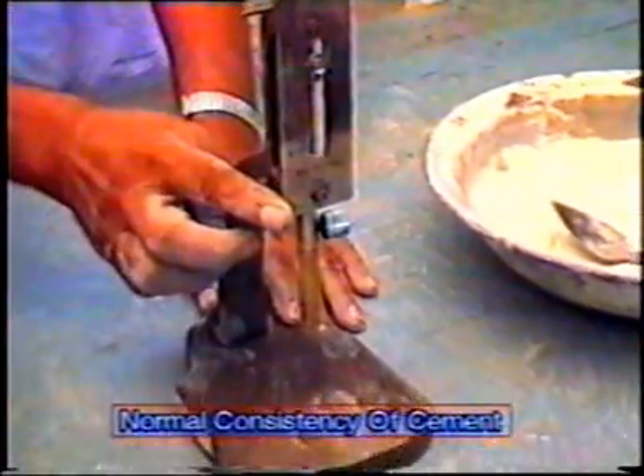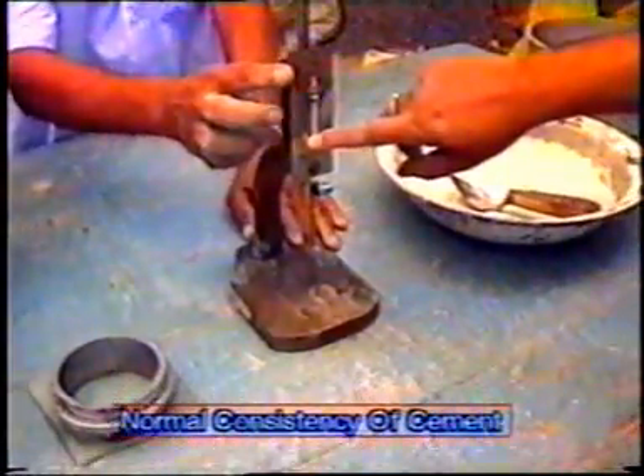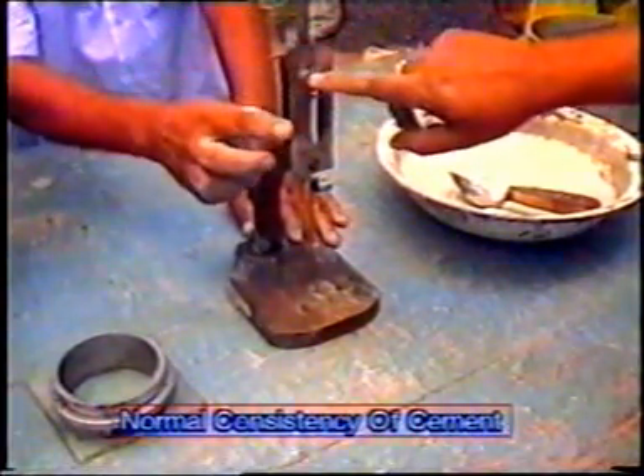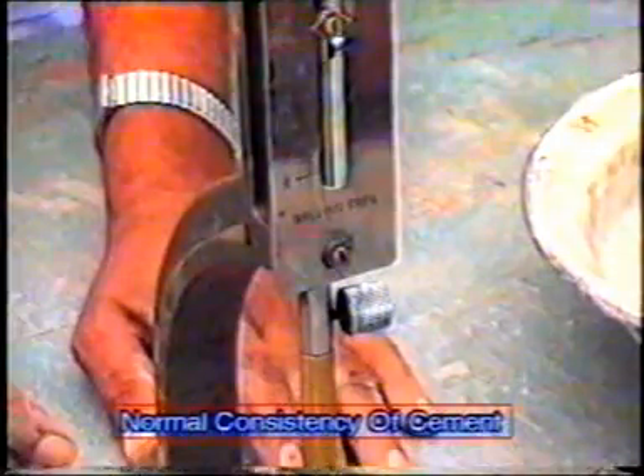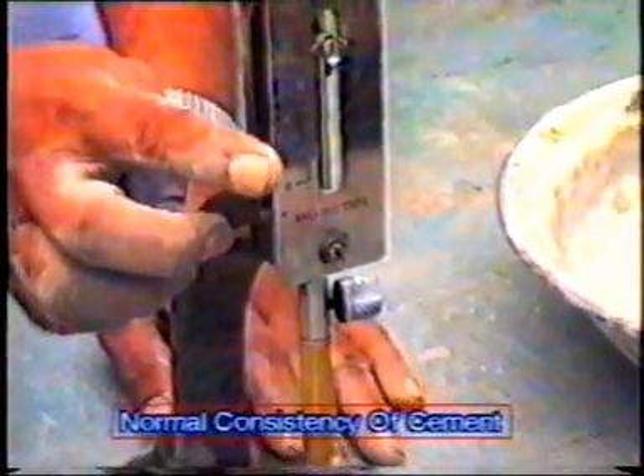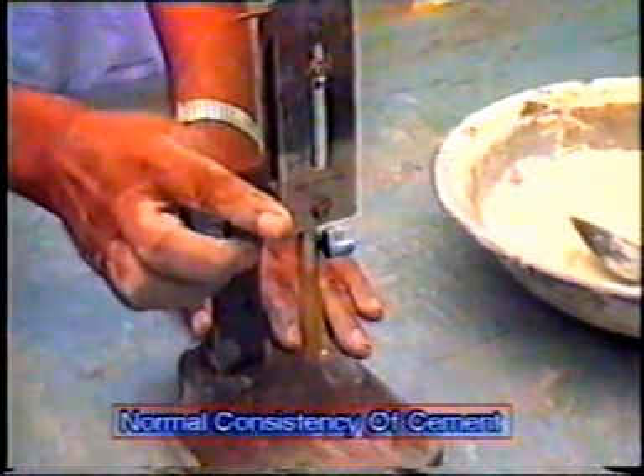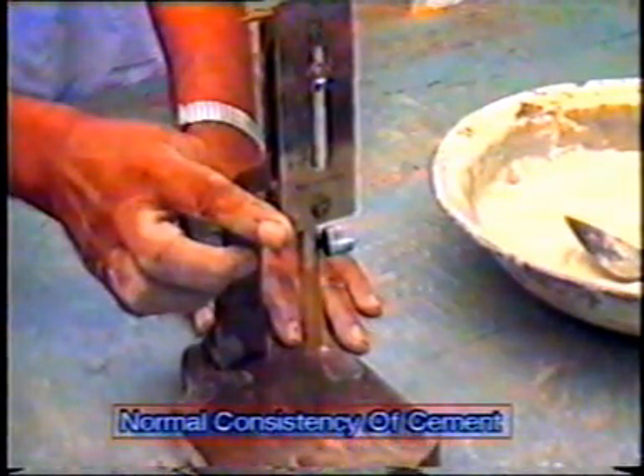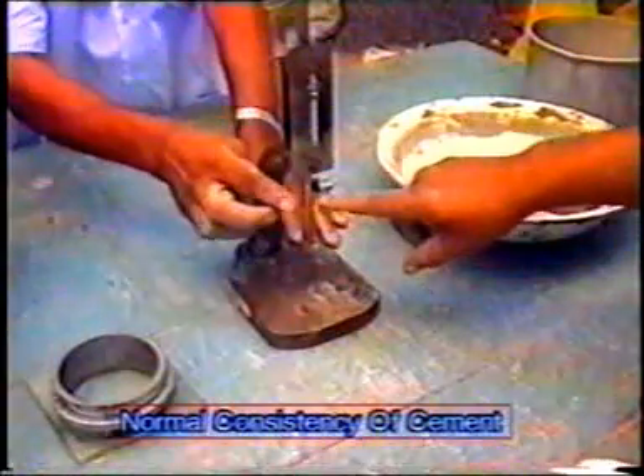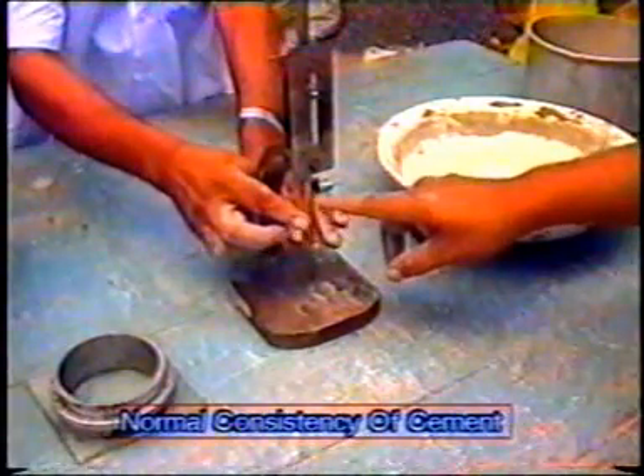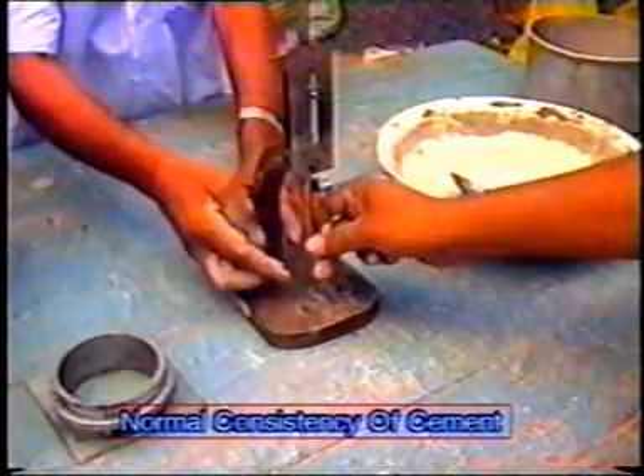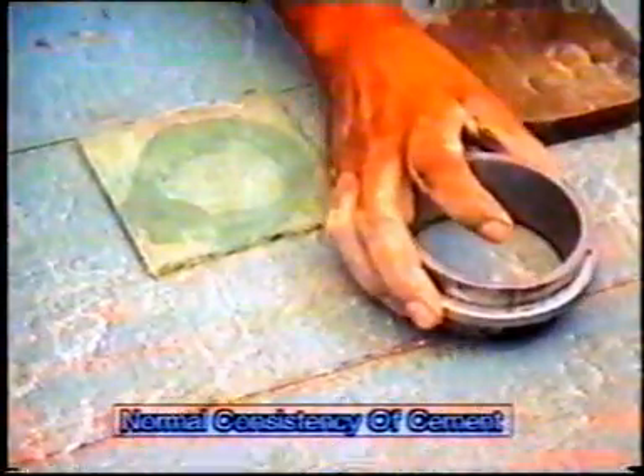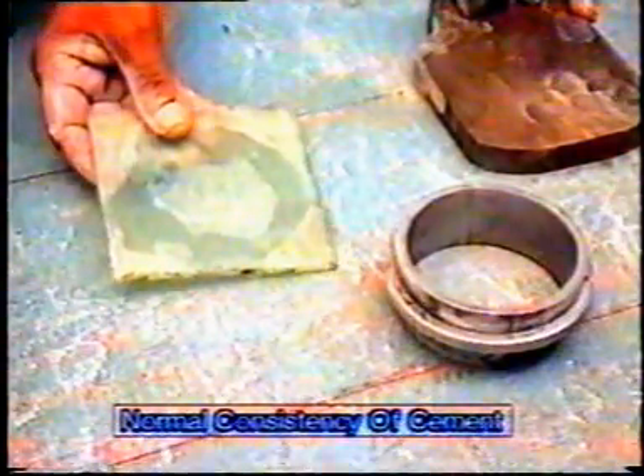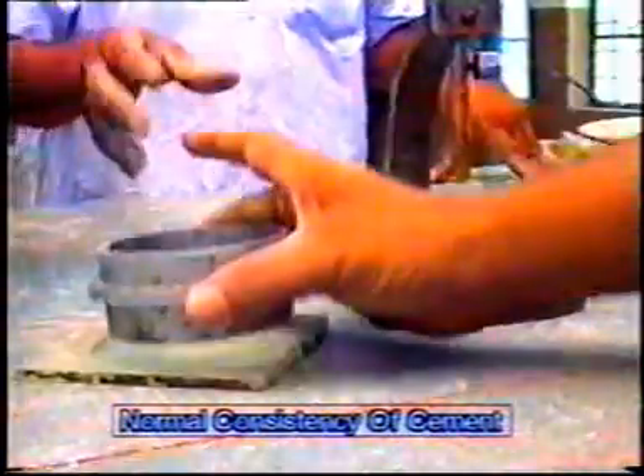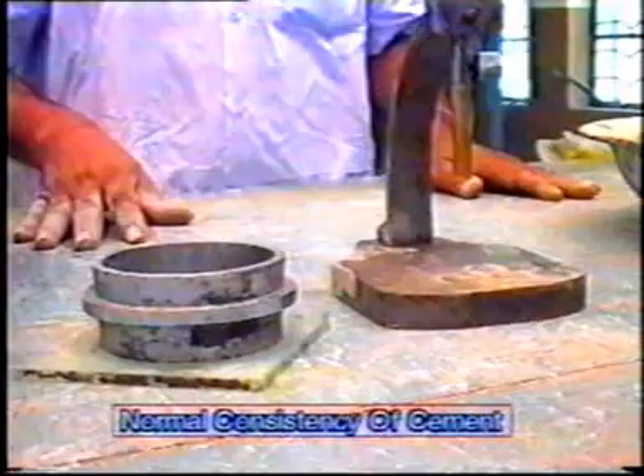Number 1, Vicat's apparatus, which is as per IS 5513/1968, whose penetration values are graduated from bottom to top, that is 0 to 50. Number 2, plunger of 10 mm diameter and 50 mm long. Number 3, mold of 80 mm diameter and 40 mm deep. Number 4, non-porous plate to place the mold and sample. Now let us see the procedure.